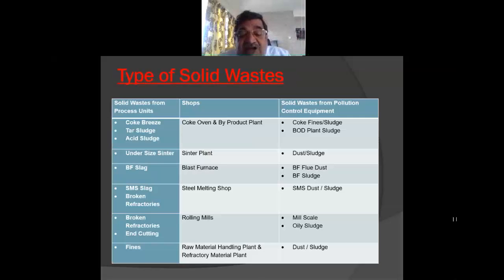Then mill scales. In the process of rolling, we do a lot of descaling. The scale which is formed on the surface is detrimental for rolling. So in the primary descalers and the secondary descalers, we take out these scales, which get accumulated in the settling tank along with the processed water. So this mill scale is also generated in the mills, and a lot of muck and debris are also generated during all these processes.